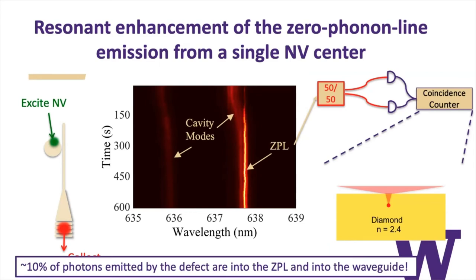Okay. And in this particular experiment, as I mentioned before, normally only 3% of the light is emitted from the defect into that zero phonon line, and it's actually emitted in all directions. You only collect a very small fraction of that 3%. And in this particular integrated photonics, 10% of the photons are not just emitted into that very useful mode, but we also showed that it goes into the waveguide where we can then route and collect it.